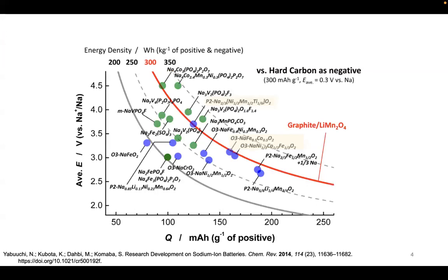In terms of what's already out there for the cathode, a lot has been done, right? You can see here for the layered type materials, this P2 layered type material, O3 type material, where you have a mixture of nickel and iron substituting for cobalt. Because if you're translating from lithium-ion battery technologies, you try to build up and translate what you've understood for lithium-ion battery materials design to that of sodium-ion battery materials design. And it's not always one-to-one, because based on what we just looked at, the sodium ions sit at both the octahedral site and the prismatic site. So clearly, when ions are intercalated and extracted, the local chemistry and the local structure is going to change, which will then also change how the crystal structure changes overall in the active material.